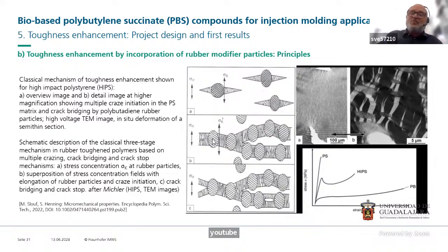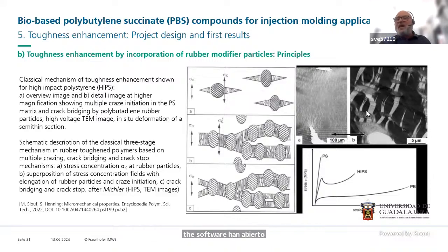Very nice. And then the rubber particles can act, for instance, as crack bridging agents. They can stabilize the cracks, and they can act also as crack stoppers. You can see that here, lower magnification. This is a polystyrene. This is not the PBS. This is our model system. We have the polystyrene, and if you add the rubber particles to the polystyrene, you can see that there are many of these deformation zones. The crazes are produced. So the energy dissipation is multiplied in a huge volume of the material, giving more toughness to the material. And you can see even here that the crack that is running in here is stopped by such a rubber particle. So that is the idea.